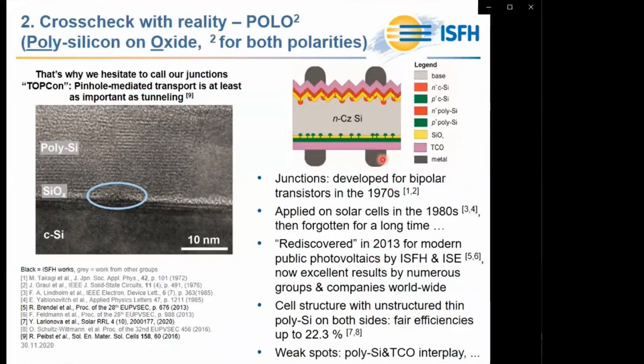Regarding the cell structure, for an implementation of both a polysilicon oxide junction collecting holes and a polysilicon oxide junction collecting electrons, you can think of the simple cell structure as a double-side contacted cell with an unpatterned polysilicon oxide junction on the front and on the rear. In this case, the polysilicon layer has to be very thin, because otherwise you would suffer from parasitic absorption, and this thin polysilicon layer may need additional conductivity provided by a TCO. With this cell concept, we so far achieve a very fair efficiency, I would say, of 22.3%. And we found in particular the interplay of TCO and the polysilicon to be much more challenging than expected.